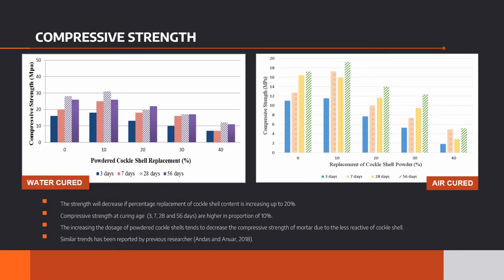First, as shown in the graph, the results show the compressive strength of powdered cockle shell mortar in two curing regimes, which are water cured and air cured. The strength of mortar in water cured is higher than air cured. This is because the water keeps the concrete moist during the hardening process. That means concrete hardens due to chemical reaction, but not because it dries by itself. However, both methods show the same pattern of results.